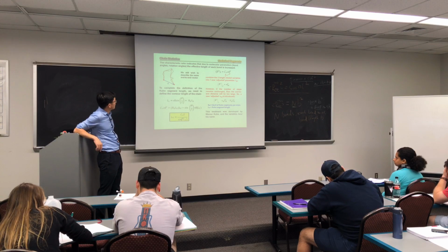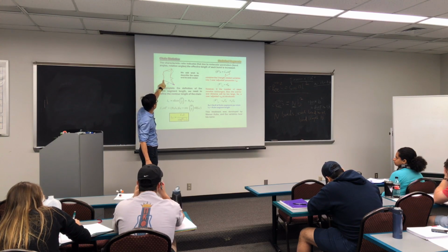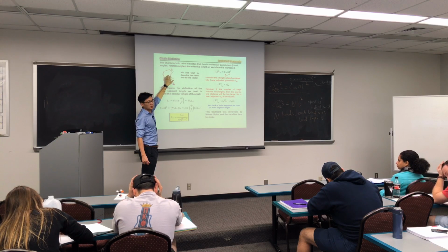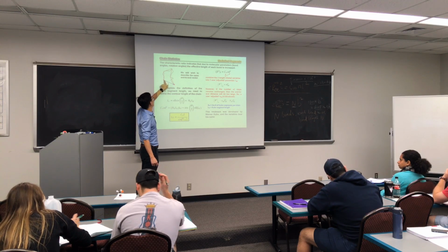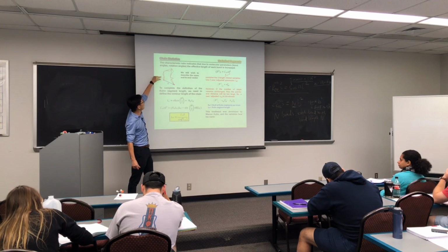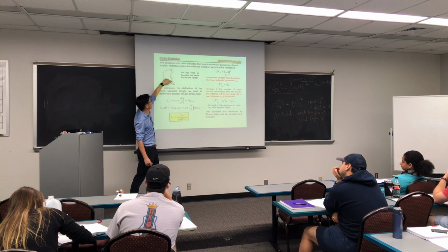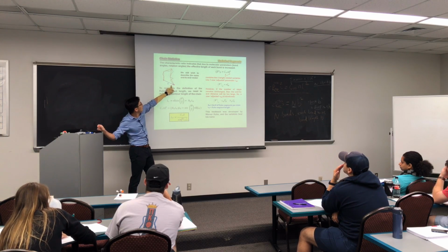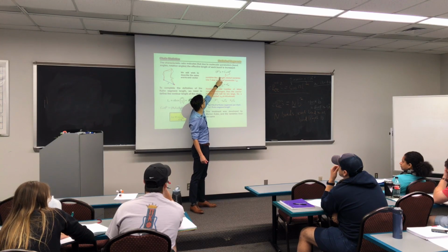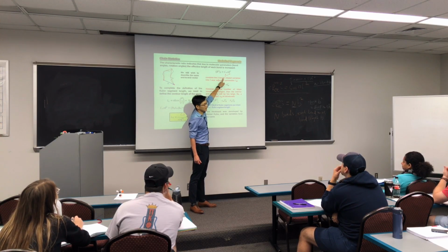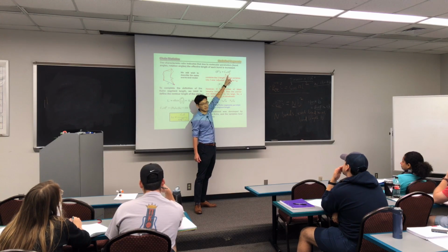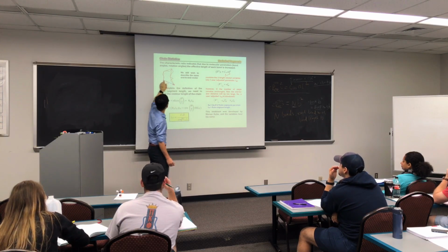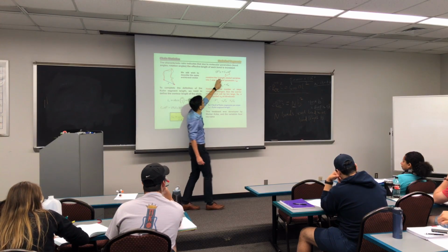In this case, the dark black one is what we originally talked about as the free joint chain model, or just a regular chain model, where each bond has a bond length as shown here. You have one attached to the other, then keep going. You would have the end-to-end distance described as this R. And R squared will be C infinity N l squared. C infinity is the characteristic ratio we talked about, because it's not a free joint chain for this particular case, for the black line. So you have to have this C infinity there.